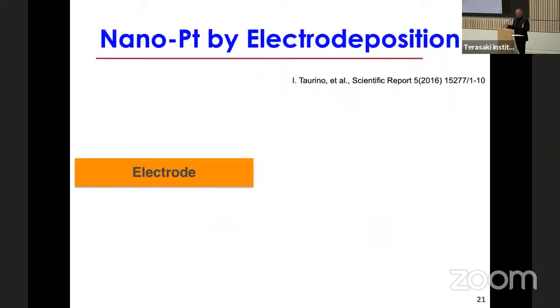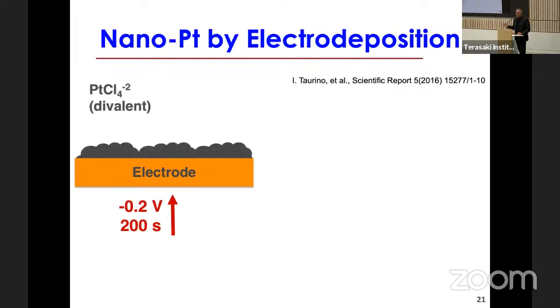As I mentioned, this is possible to be done on electronics, but it's tough. We run the risk to burn because we are approaching 450 degrees. So what about alternatives? For example, nano platinum or nano gold. It's very easy to grow directly on the working electrode just by electrodeposition from salts.